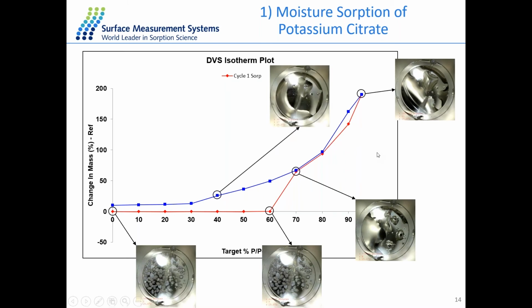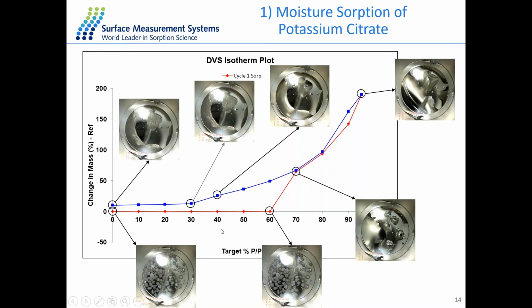During the desorption step, it stays in liquid form until 40% RH. And then at 30% RH, there is a sudden crystallization of the material. Then the mass change of the sample doesn't change anymore between 0 and 30%. And at the end of the desorption step it is in a crystalline form as well, rather than the particle form at the very beginning during the sorption step. So we can easily study this kind of morphology change with humidity, with the combination of the DVS and the video function. And it can give a really good idea about how the morphology will change along with the different humidity.